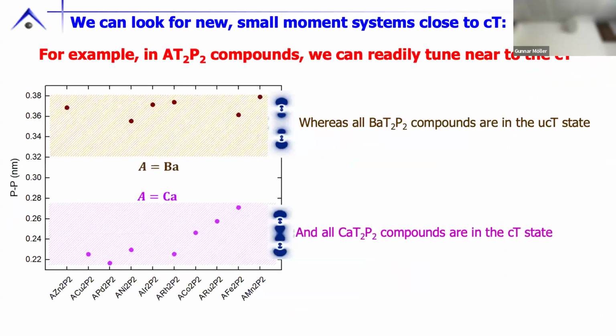So I can look at the AT2P2 materials. I can look at the barium examples, and all of these have PP distances that are in the unbonded regime. If I look at the calcium, all of these have PP distances more consistent with bonding.